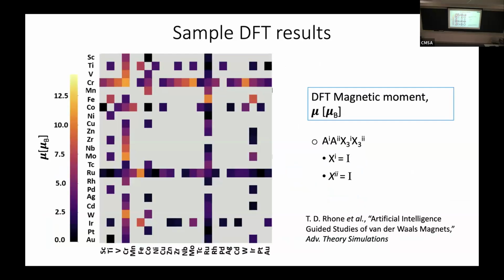So here are some results with the A1 substitution on the horizontal axis, the A2 substitution on the vertical axis. The color here is now the magnetic moment, which is like the magnetization. There are these gray squares, which are missing data, materials where we don't have material simulation calculations. To give you an idea, each square is a different material. So this one is chromium 2. I forgot to say both X sites for this panel are iodine. So this is chromium 2, I6, or chromium triiodide. Notice that there are patterns in the data. We'd like the AI to learn the patterns for quantitative predictions.